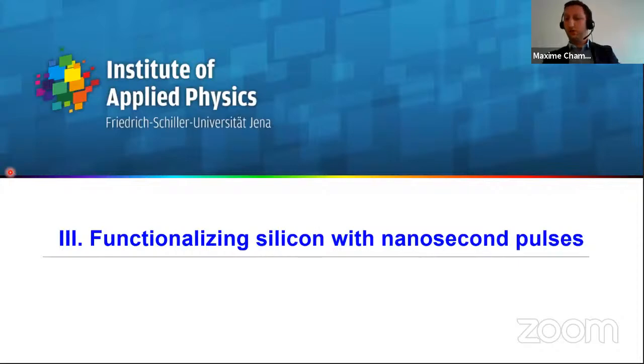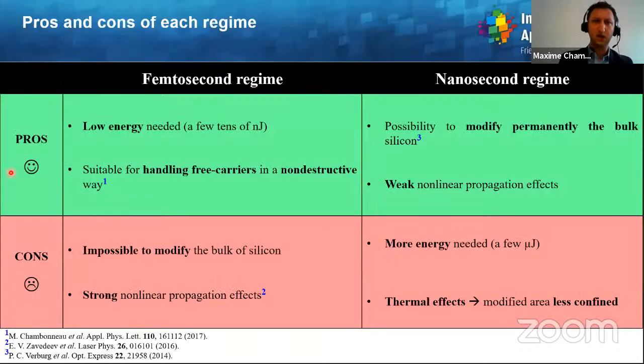So now a second study was oriented on the functionalization of silicon with nanosecond pulses. Why? Let us summarize and evaluate the pros and cons of each regime. In the femtosecond regime, as we have seen, a low pulse energy is needed, and it is suitable for handling free carriers in a non-destructive way in microelectronic devices. However, the cons are, of course, that it's impossible to modify the material inside the bulk. This is due to strong nonlinear propagation effects.